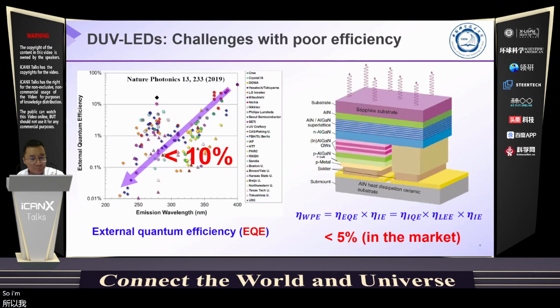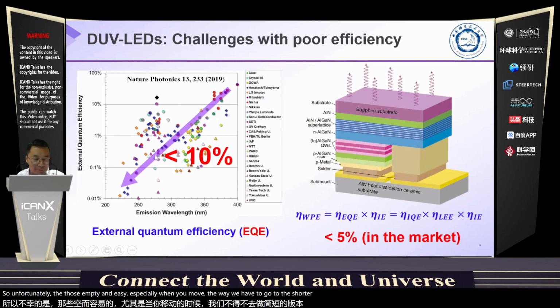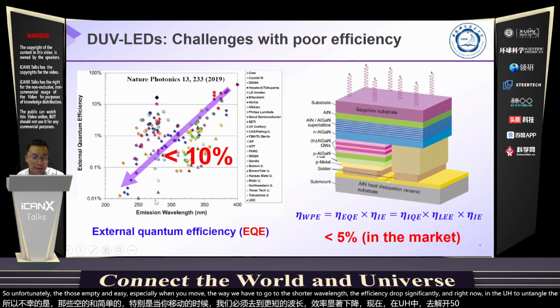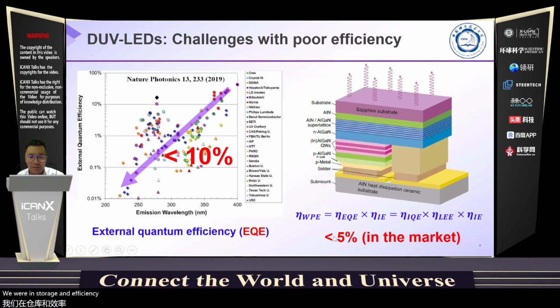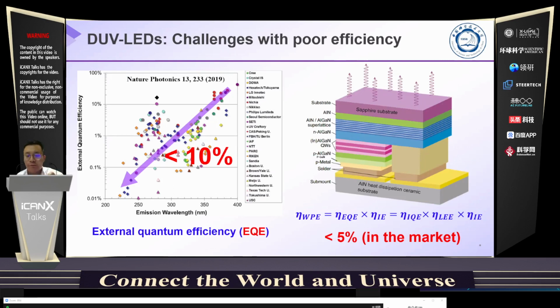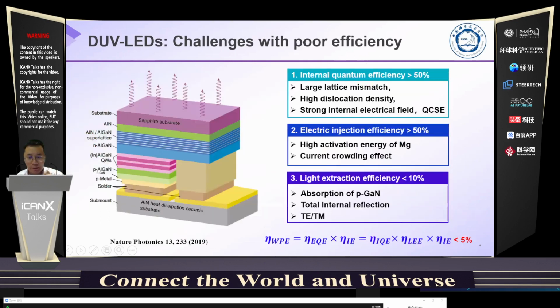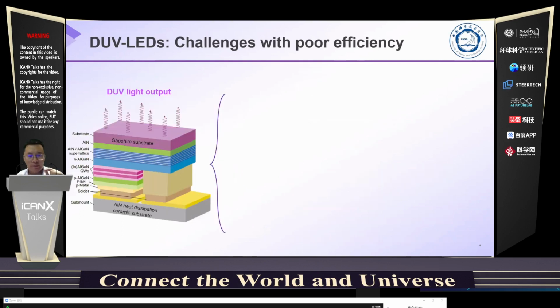Unfortunately, for those LEDs, when you go to shorter wavelengths, the efficiency drops significantly. Right now in the 250 to 280 nanometer wavelength range, the efficiency is less than 5%. This is too low compared with blue LED chips, which have an efficiency of more than 50%. So we wanted to improve it. There are many factors to be considered: how to improve internal quantum efficiency, how to improve electrical injection efficiency, and how to improve light extraction efficiency. All those factors play a role in a highly efficient LED.